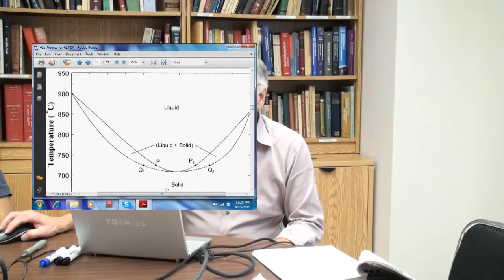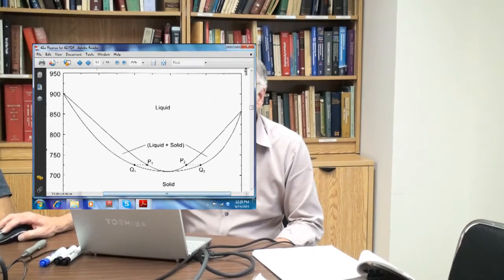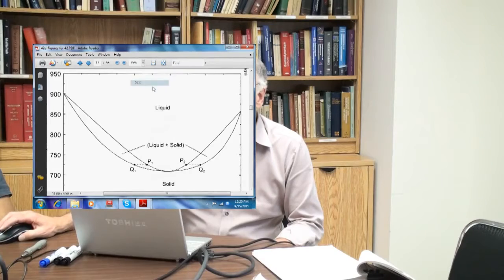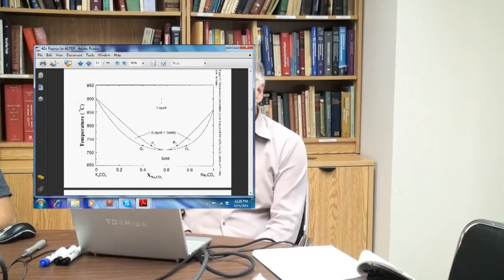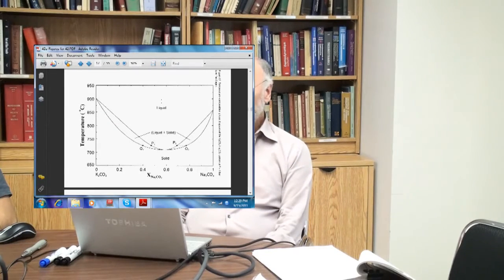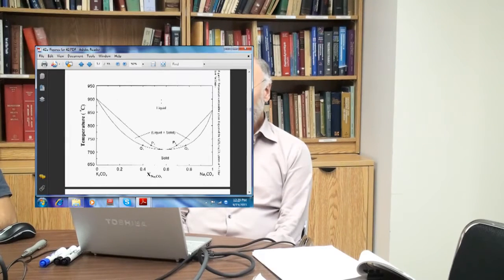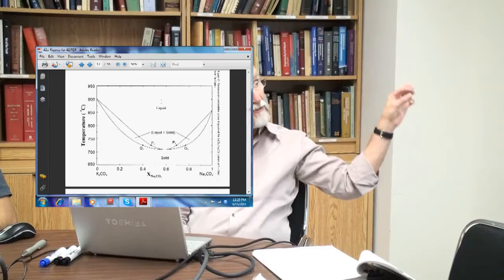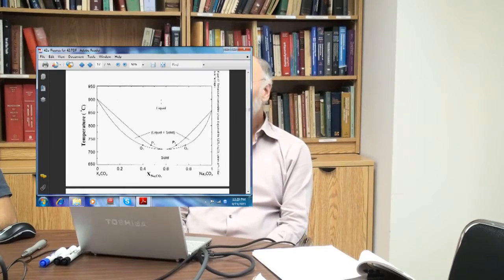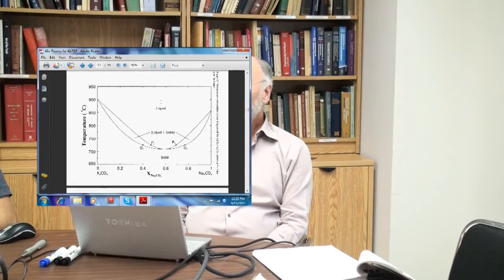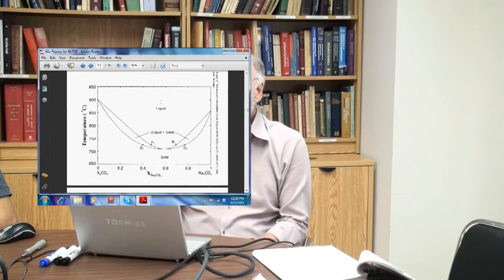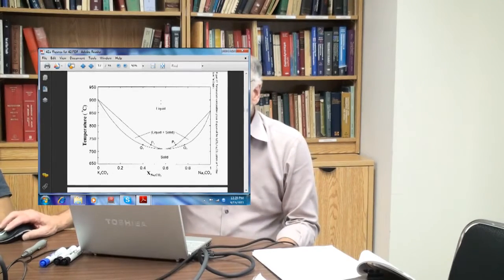Okay, here's an actual system here. This is the potassium carbonate, sodium carbonate phase diagram. It's a two-phase region. You have complete liquid miscibility, complete solid miscibility, but rather than having a lens-shaped two-phase region, you actually have a minimum in it with liquid and solid regions on the two sides. Okay? So how do we explain that?